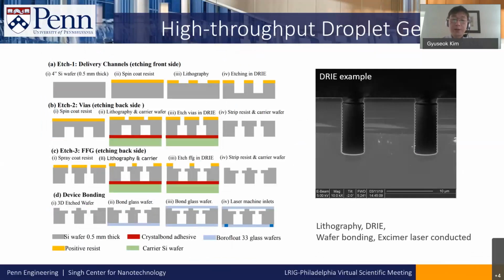And the key difference, so now think about the fabrication process. They didn't use the conventional soft lithography fabrication technique. Rather they used deep RIE. If you remember, with deep RIE you can etch silicon at very high speed. So they used the deep RIE tool actively, and they made big channels from both the front side and back side, and did glass wafer bonding. They also used an excimer laser to punch through the inlets and outlets, and they were able to make this for biological applications.